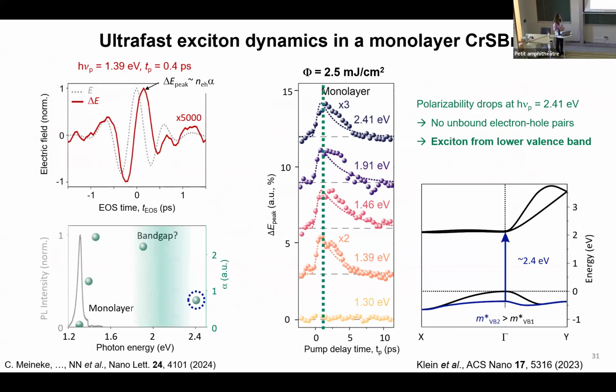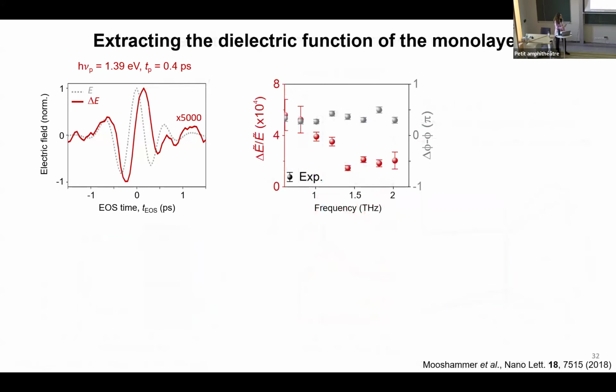So where was I? Okay, I've discussed the possible band structure of the monolayer, and there is yet another information that we can gain, and this is why I called, like with SNOM, we can measure the dielectric function. Here is how we can actually obtain it. The information that we want is all recorded in this scattered terahertz electric field. We can study it in the time domain, as I showed you, to retrieve the relaxation dynamics. We can also Fourier transform our scattered terahertz pulse and retrieve information in the frequency domain.